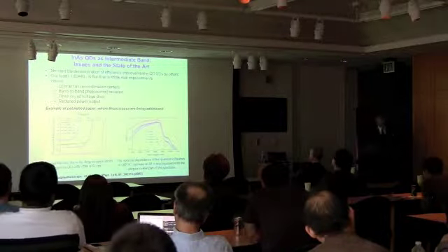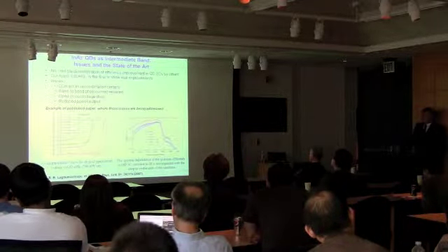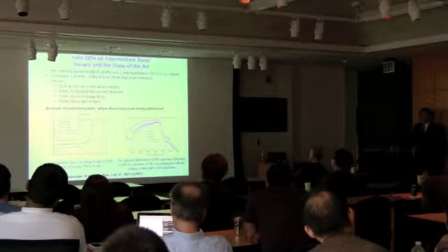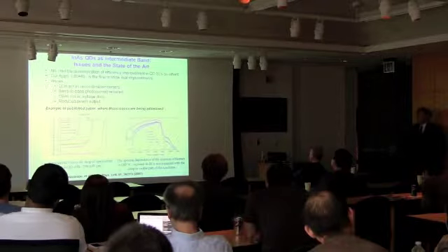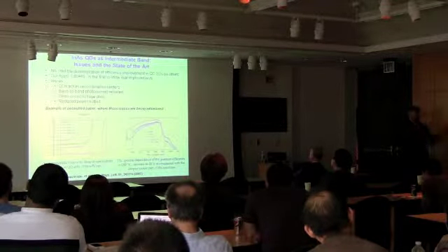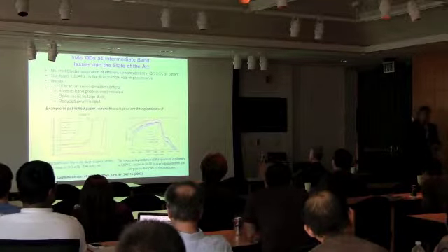So what we suggest, to overcome this problem of reduction of current, and what is most important here, is that you immediately understand our idea: when you increase the absorption there, then the efficiency from the higher-energy photons inevitably goes down, because electrons and holes produced by these previously important photons can now recombine.